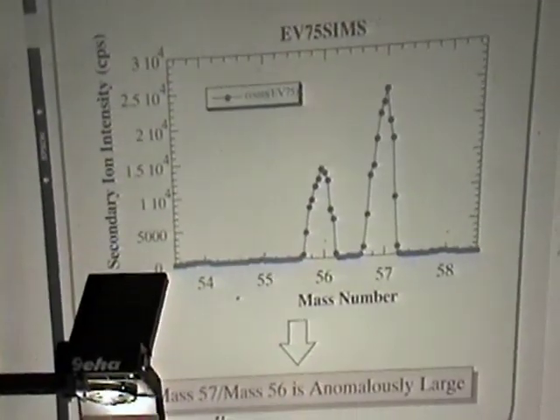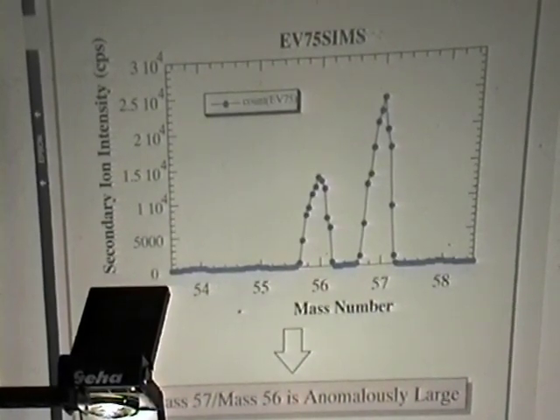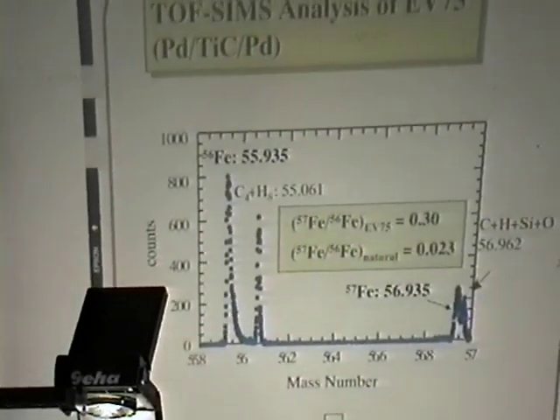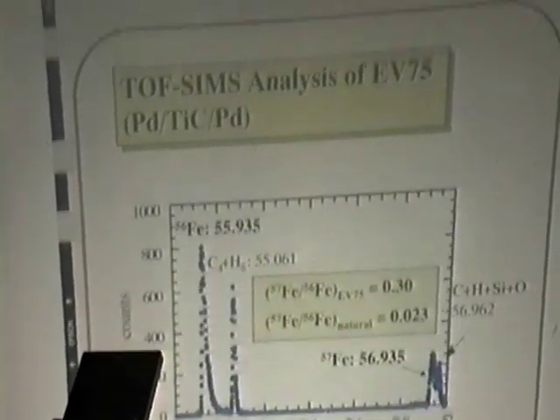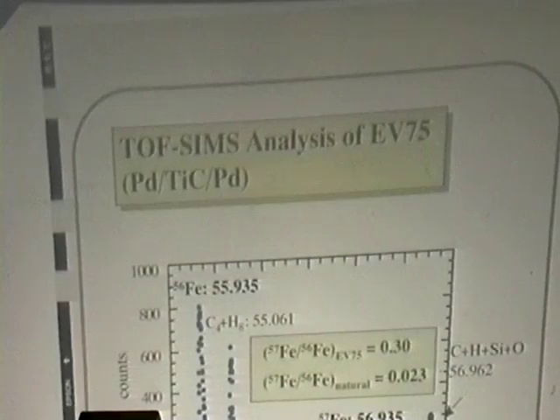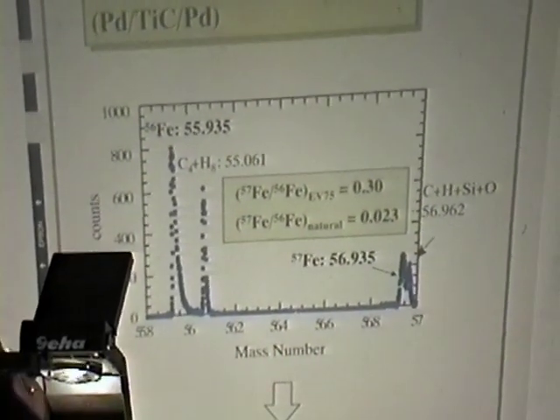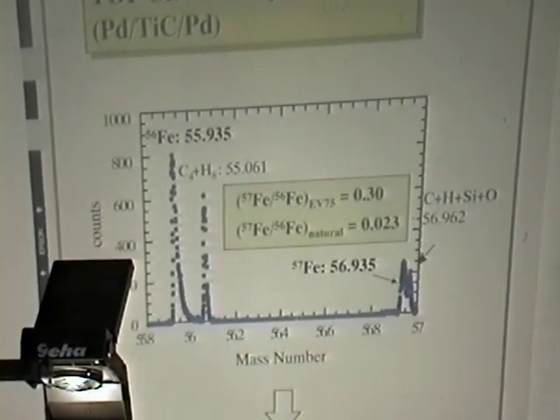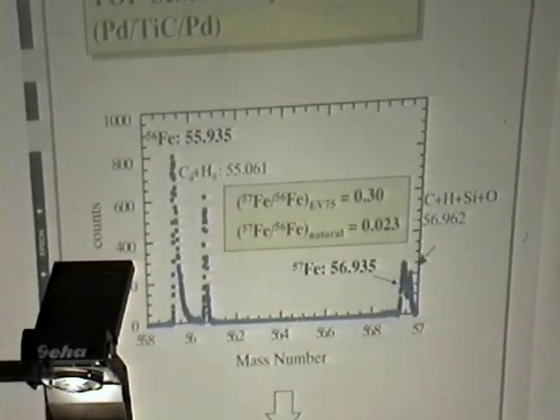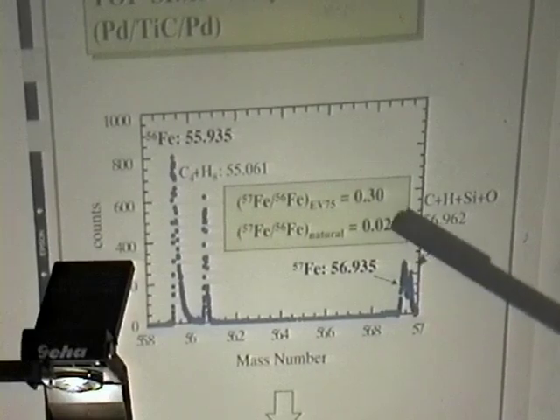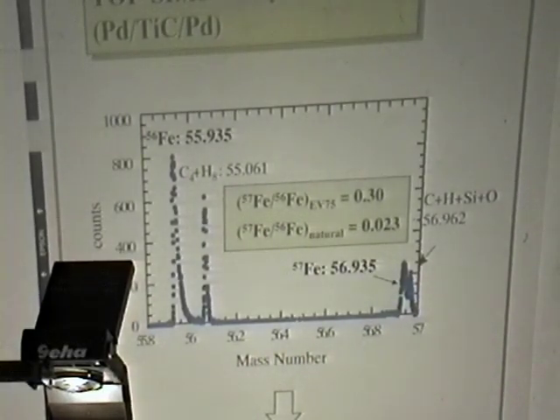This is a SIMS analysis of EV75. We can see the 56 and 57 peaks here. So iron 57 by iron 56 is anomalously large, as you can see. This is the time-of-flight SIMS analysis of EV75. With time-of-flight SIMS, we have good resolution, so we can identify iron 56 and iron 57. We can see iron 57 by iron 56 is larger than natural abundance. So the anomalously large Fe57 by Fe56 is confirmed by both SIMS and time-of-flight SIMS.